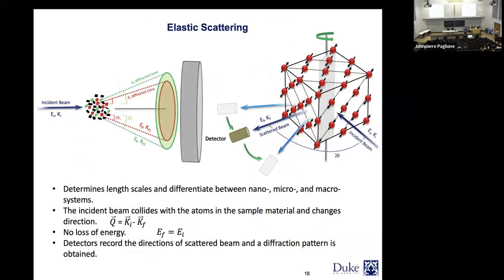So this diagram is basically for a powder sample. It's as if you have a lot of different tiny single crystals, right? Each of them is oriented differently, so it's going to give you the Bragg reflections at different places, with a detector at the different areas of it. But if it's coming from the same d-spacing, they're all going to be sitting on one circle.